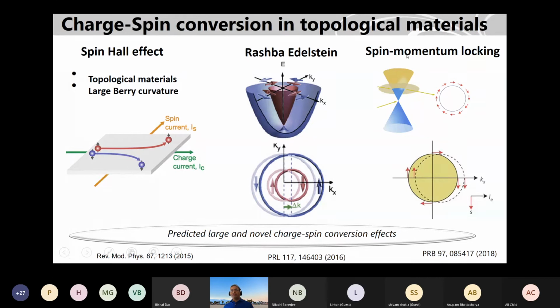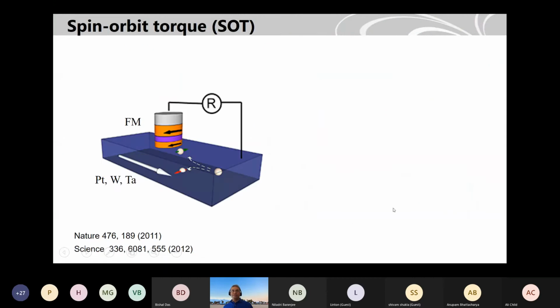And in the Dirac topological material system, it's actually the simplified version of this. So instead of two bands, you have only one band at the surface, and that is also spin momentum locked. And this gives the spin polarization. When you apply an electric field, you create the spin density.